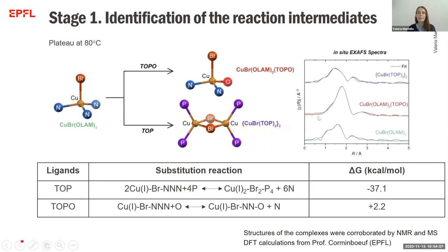during the first stage. And based on these spectra, what we found out is that copper bromide and oleylamine, which represent the initial reaction mixture, form a pseudo-tetrahedral structure, which undergoes a complete ligand exchange with TOP to form a bimetallic complex, and partial ligand exchange with TOPO to form a monometallic complex. And also the DFT calculations were in agreement with the substitution of oleylamine by TOP being extremely favored, even at room temperature. Instead, the substitution of oleylamine by TOPO possibly occurs when we increase the temperature.